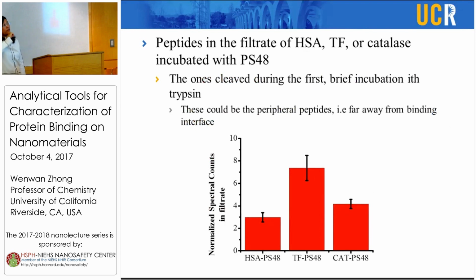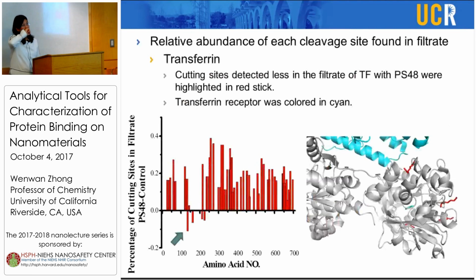So what we see is that for the peptides in transferrin and also catalase, which show higher fluorescence change and very rapid protease digestion, we indeed identify more peptides in the filtrate compared to HSA when incubated with polystyrene particle. And if we analyze the cutting sites affected by protein binding, by comparing the cutting sites identified for the protein remaining bound on the particle and the protein in the filtrate, and illustrate the position of those peptides on transferrin, we see those are structures labeled with a high B factor, which have high flexibility, so they are being affected.